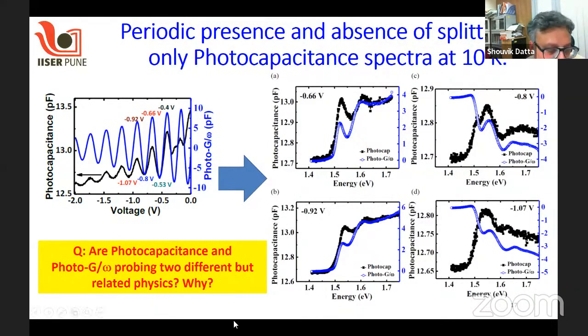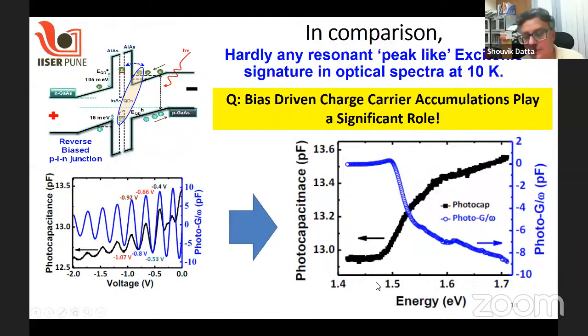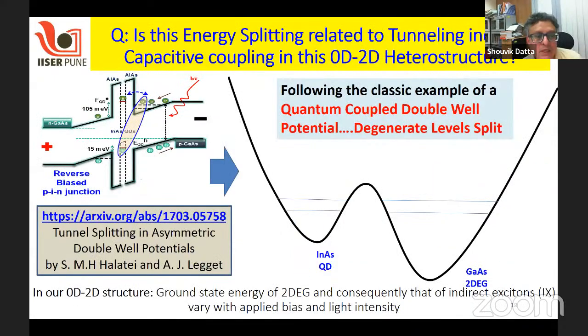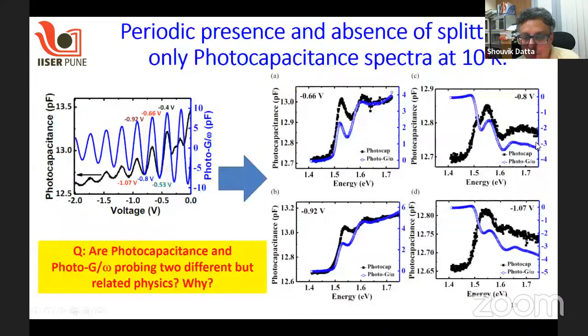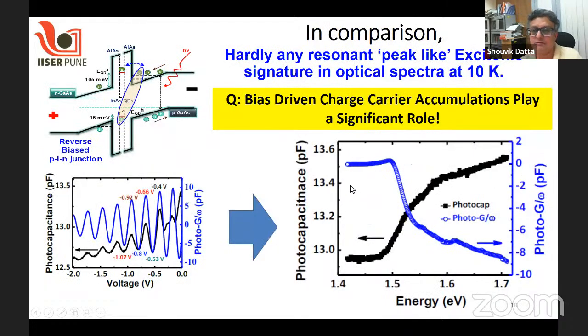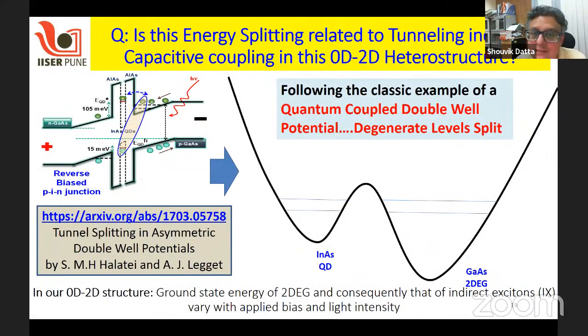And obviously there is one question: are photocapacitance and photoconductance probing different but related physics, and why? We don't see much of a resonant peak-like feature of excitons in spectra taken at zero bias. So it shows that bias-driven charge carrier accumulation does play a significant role in these measurements. And it struck us to probe whether the energy splitting that we see at the photocapacitance maxima is related to the energy splitting that can happen when two nearby quantum wells are coupled, like a double quantum well potential.